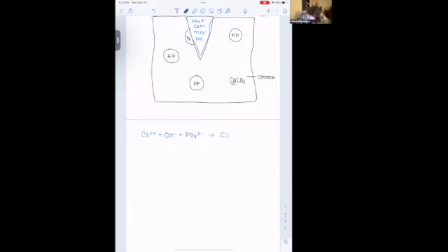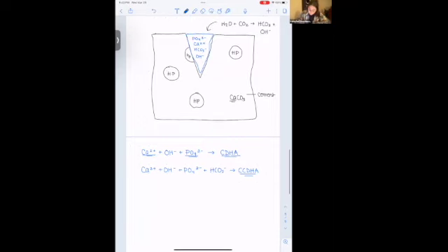So if you ended up having calcium plus the hydroxide, and then the phosphate, then you'll probably end up with CDHA, so calcium deficient HA. And again, that's just due to the amount of calcium that's available versus the amount of phosphate that's available. But if you end up substituting some of the phosphate for the carbonate, they were able to form CCDHA. And together, those two forms of hydroxyapatite filled the crack and they were able to get 95% healing.